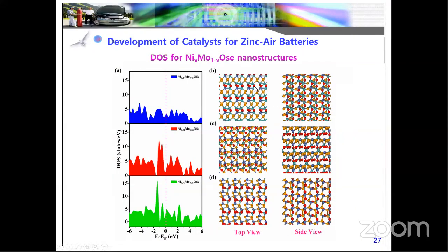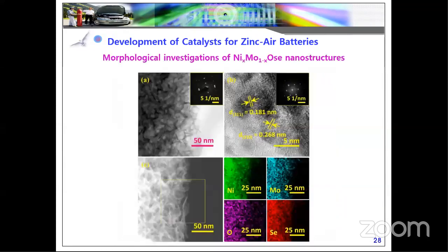So after fabricating the materials, we need to prove not only by the experimental but also by the theoretical studies. From the theoretical studies, we mixed different ratios, and finally we got the 1:1 ratio of nickel and molybdenum. You can see the intensity is very close, and the energy is very high compared to other materials. From the studies, we can say our material is highly active, and this material can be applied as the air cathode for metal air batteries.